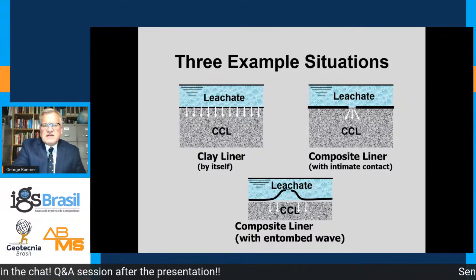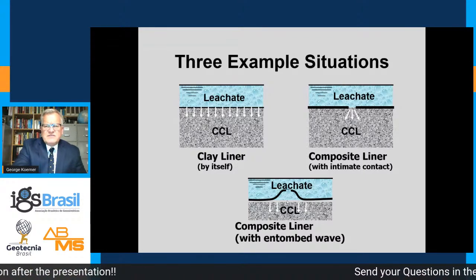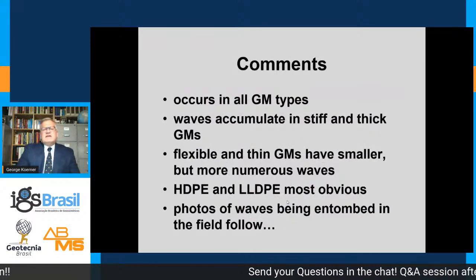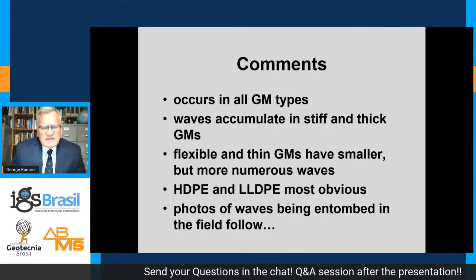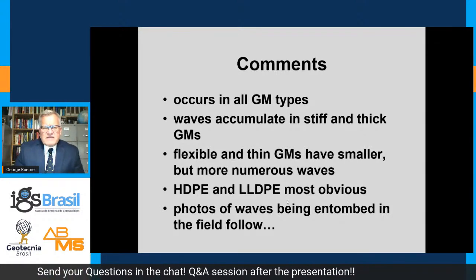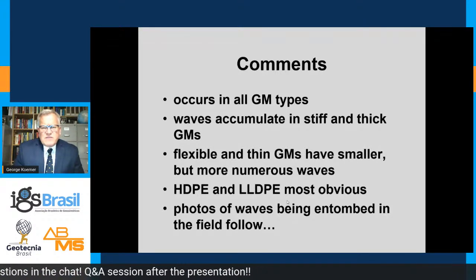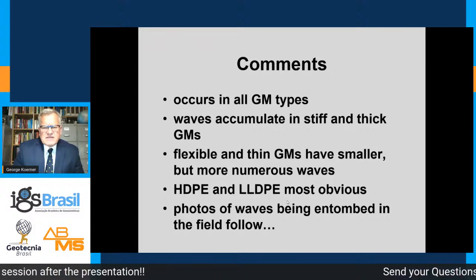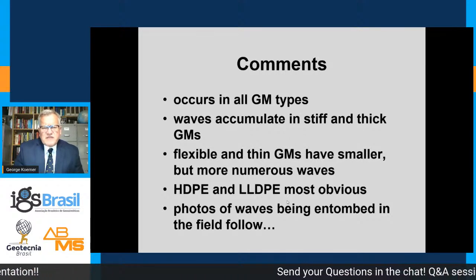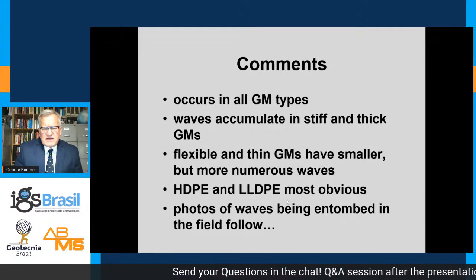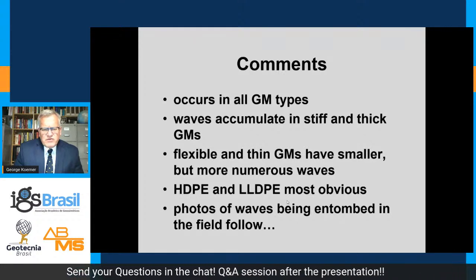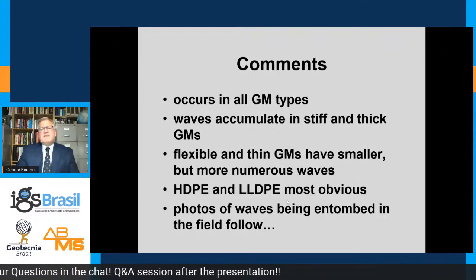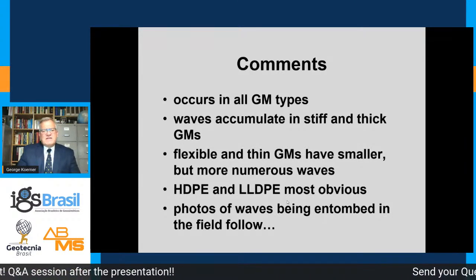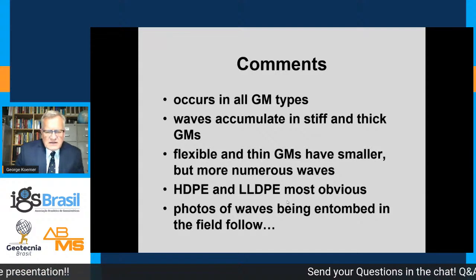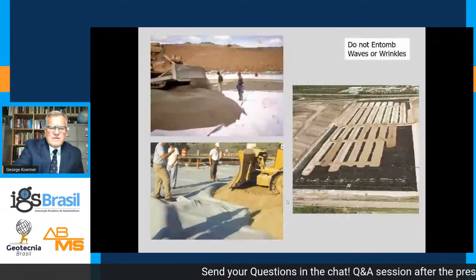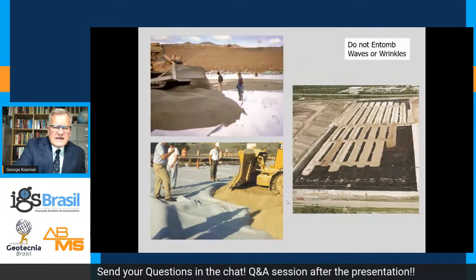So ultimately, you would like a press fit of the geomembrane against the underlying clay. This occurs in all geomembrane types. Waves accumulate in stiff, thick geomembranes the most. They occur in flexible membranes, but they're smaller, but more numerous. They're very obvious in all the polyethylenes, both HDPE and linear low density, and entombing these waves is problematic.